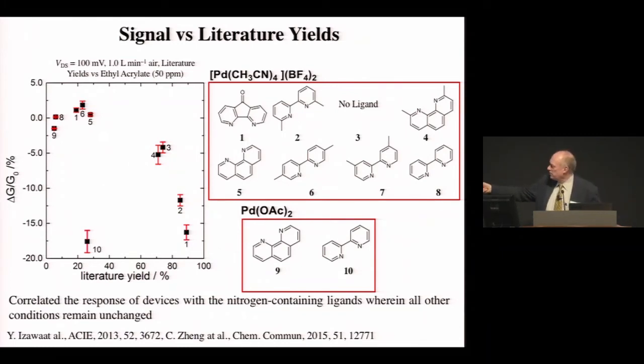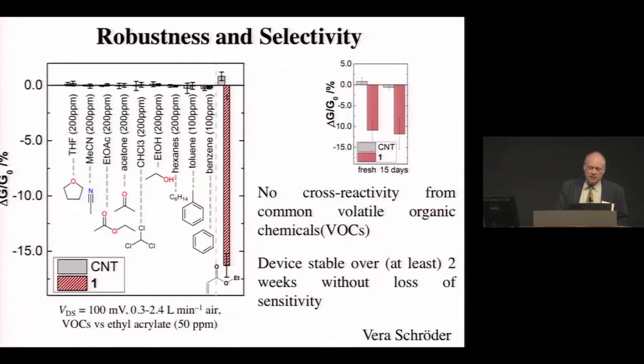We have an anomalous situation here with palladium acetate and this bipyridyl. We think there's a side reaction going on there that's giving us this large signal. But nevertheless, this really mirrors what Shannon had found, and it also has very good specificity. Reactive alkenes like ethyl acrylate have very large responses. The polar end of the molecule is what usually interacts strongly with the nanotubes. But if we take its close cousin that's just missing this double bond, you see we're really at baseline. So we actually have a way of getting very high selectivity by making use of organometallic chemistry.